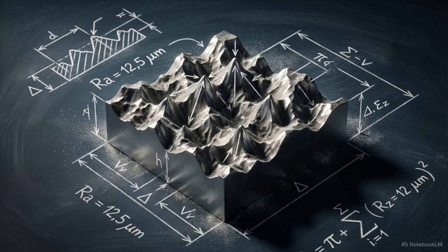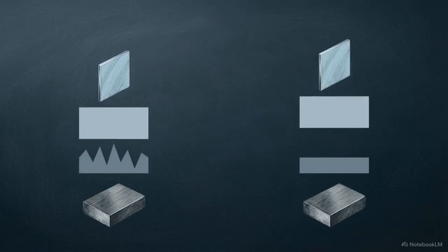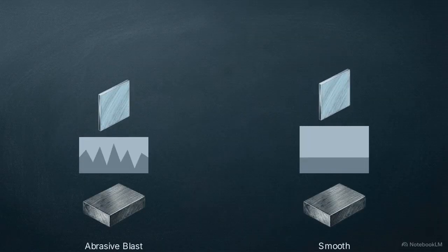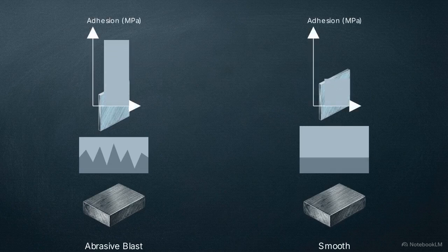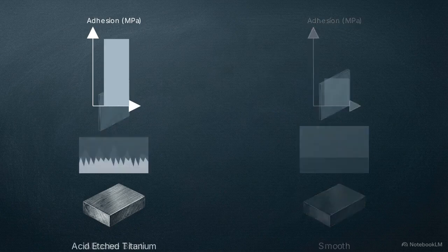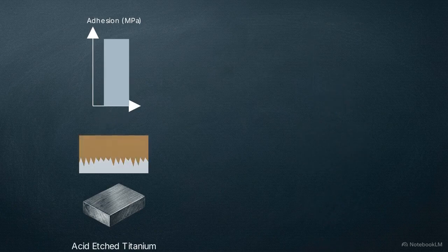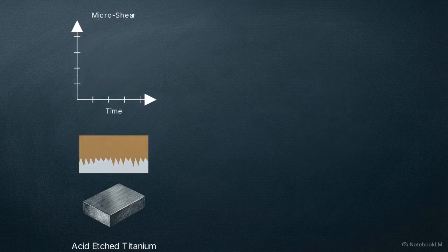They validate the microscopic surface preparation that occurred before the coating was applied. For example, abrasive blast cleaning increases surface area to promote mechanical interlocking. Data from pull-off and tape X-cut tests consistently show that these jagged surface profiles yield the highest adhesion scores. Chemical preparations work similarly. Strong acid etching alters the micro-shear strength properties at the boundary, optimizing the adhesion between a resin and a titanium substrate.